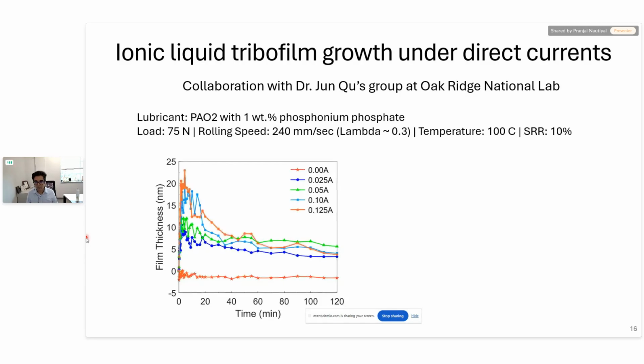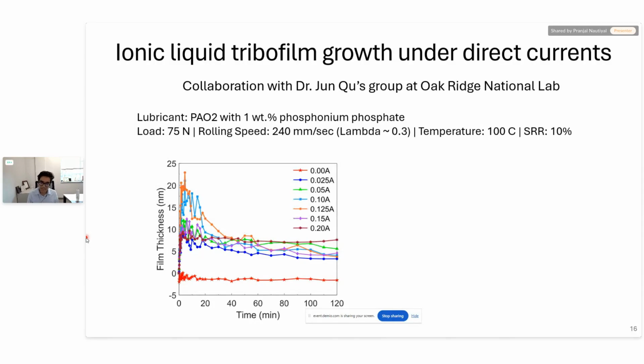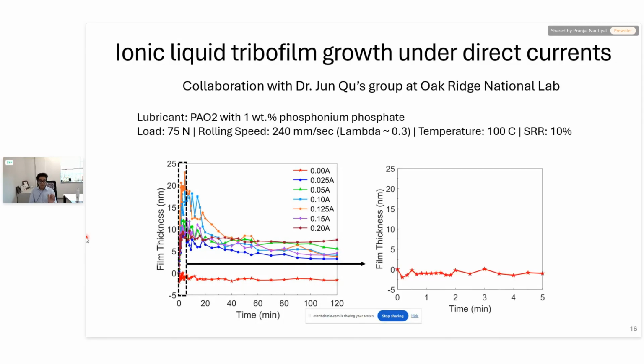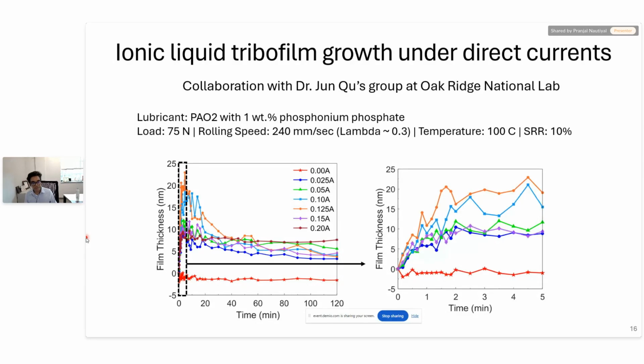We saw this behavior until 125 milliamp, where the application of current enhanced film growth kinetics and produced thicker tribofilms. However, when we further increased currents to 150 milliamp, 200 milliamp, the growth kinetics was actually suppressed. So we did not see further benefits of applying electric field through the ball disk interface. We can zoom into the early 5 minutes of the experiment, which is where most of the film growth takes place. And again, I can show you very clearly here, the growth kinetics of the tribofilm increases initially up to 125 milliamp, but then further increase in current actually resulted in thinner films. So the effect of that enhanced tribochemistry was suppressed after a critical current value.